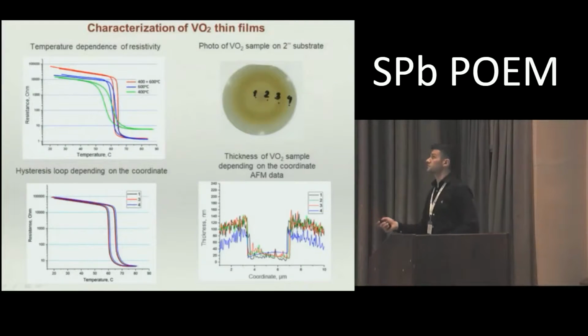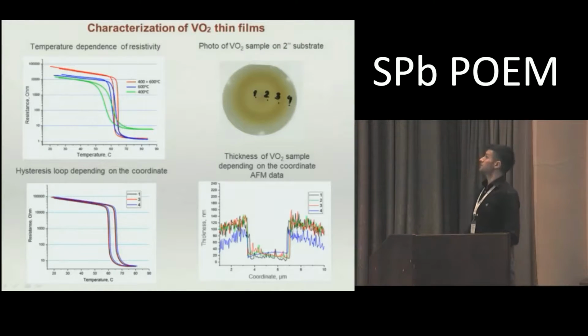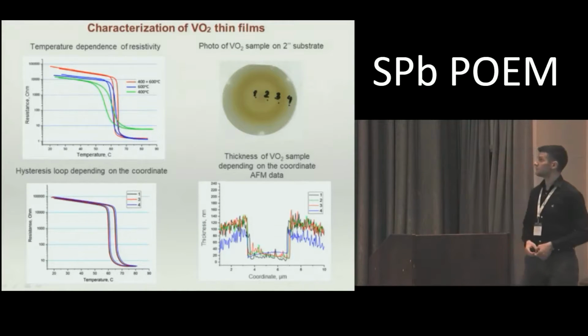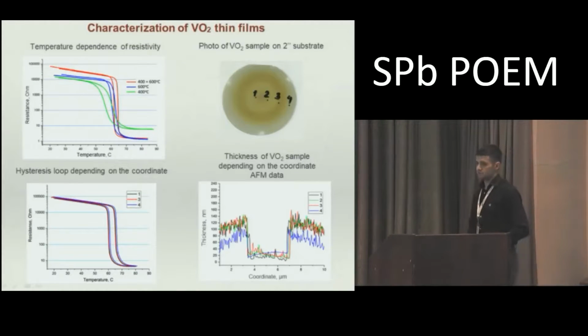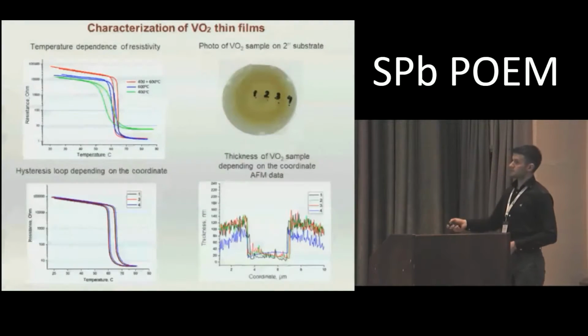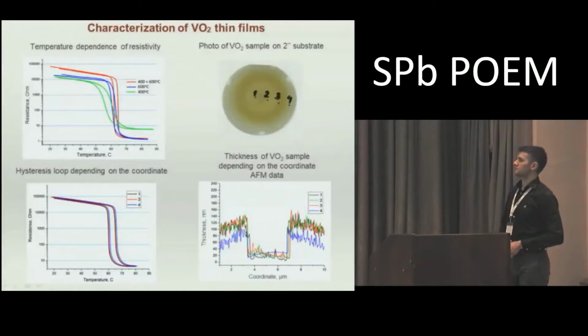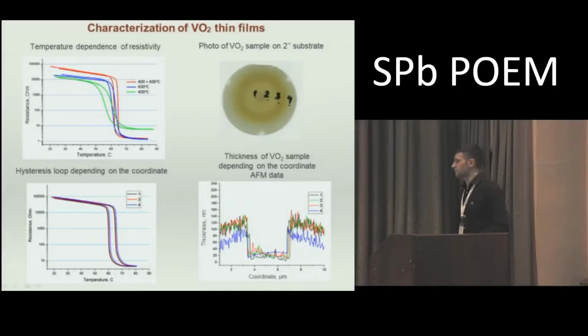Here is a photo of a 2-inch sample of vanadium dioxide on a sapphire substrate. At different points, I show the thickness of the sample depending on the radius. We see that there is no large difference in thickness between the center of the sample and the edge. It was about 100 nanometers. The same is true for the hysteresis loop of the resistance. We have no difference between the middle of the sample, the center of the radius, and the edge of the sample.